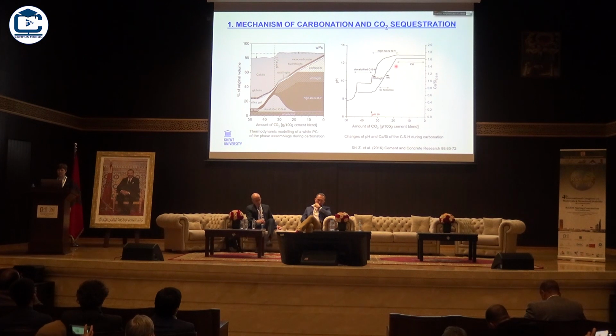And at the right-hand side, at the same time in this image, you can see the related drops in pH in the black curve and then in the more gray curve, the change in calcium-silicon ratio in the calcium silicate hydrates. So as long as Portlandite is reacting, the pH is more or less stable, and also the calcium-silicon ratio. But then if all Portlandite is transformed into calcium carbonate, other reactions are starting, and most importantly, the high calcium CSH is transformed into decalcified CSH. So calcium oxides are taken from the CSH to form more calcite. And that means that at this time the pH will drop first slowly, then more rapidly, and at the same time the calcium-silicon ratio in the CSH will go down.